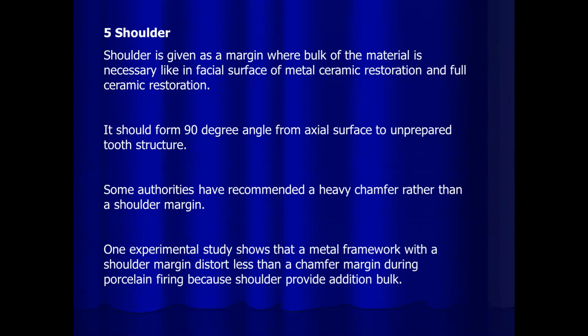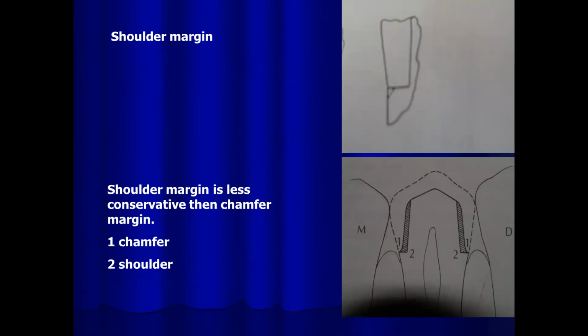Some authorities have recommended heavy chamfer rather than the shoulder margin. One experimental study shows that the metal framework with the shoulder margin showed less distortion during the porcelain firing because the shoulder provides additional bulk. In shoulder margin, a straight flat end taper burr is used. You can see in the second image and also in the first image, this is the 90 degree angle. So a flat end tapered burr, a long tapered burr, is used for this margin.